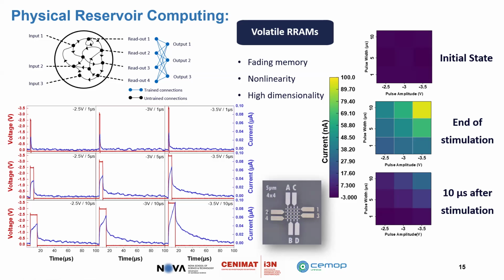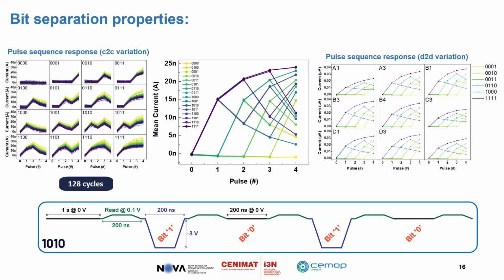This is a zinc tin oxide device, so we don't use just HZO. We also moved to greener technology, using only zinc tin oxide here, and we fabricated a small crossbar, and started to apply different pulse stimuli and see the increase of the current, and the fading memory characteristics here. So devices are completely nonlinear. We started to have pulse sequence responses and different cycle-to-cycle variations. This means for each sequence we have a certain pulse scheme. For example, one can be a pulse of -3 volts to our devices with a certain length, and then a read at 0.1. Then you change different sequences and you are dealing with a different signature of these devices. We also checked the cycle-to-cycle variation and the device-to-device variation.